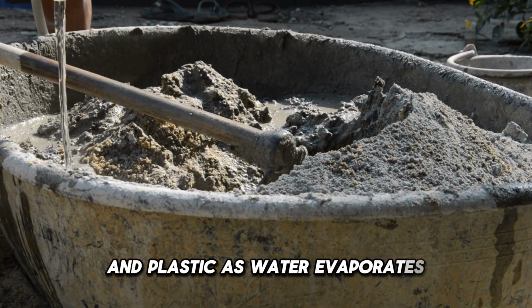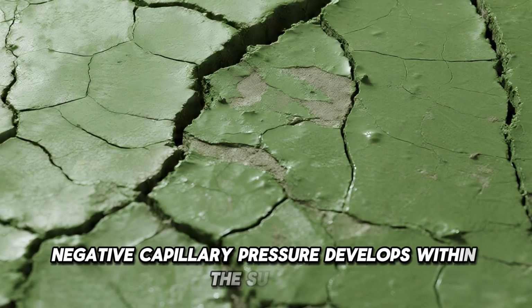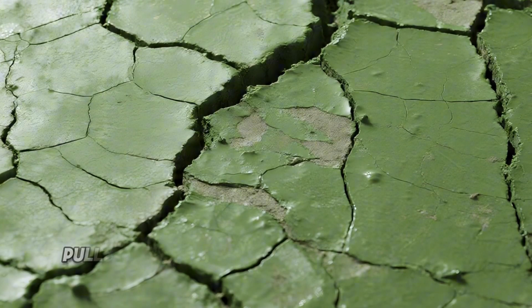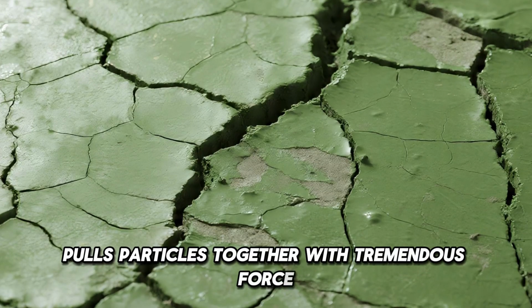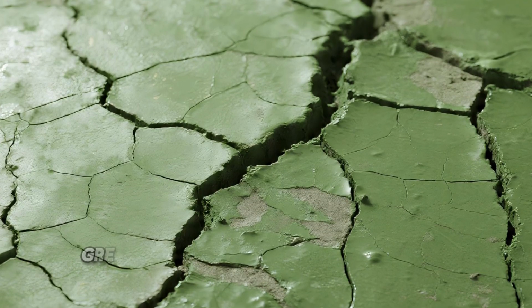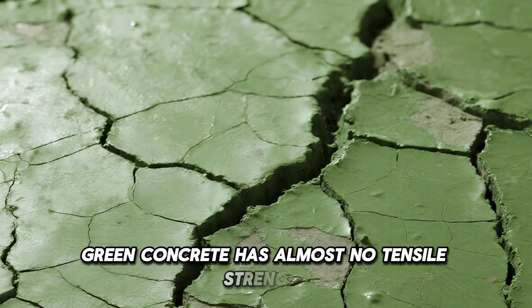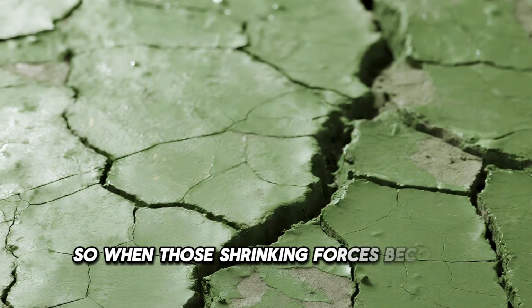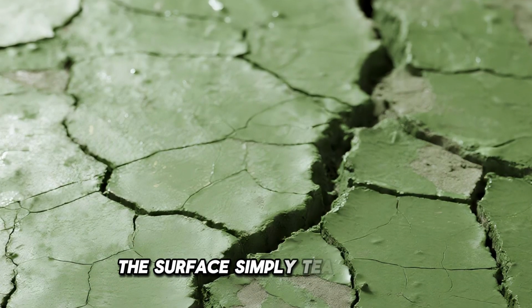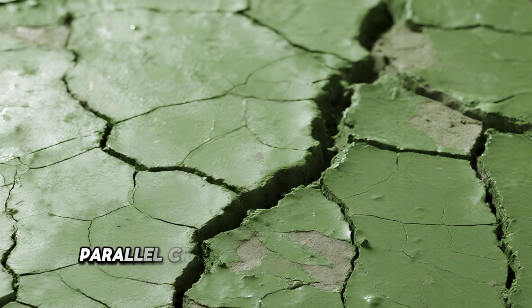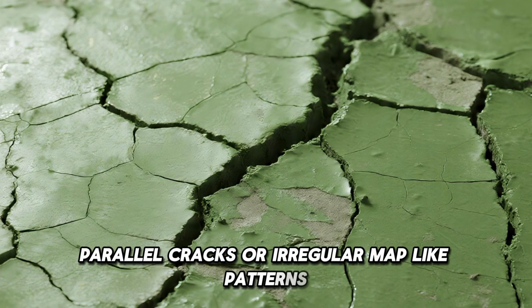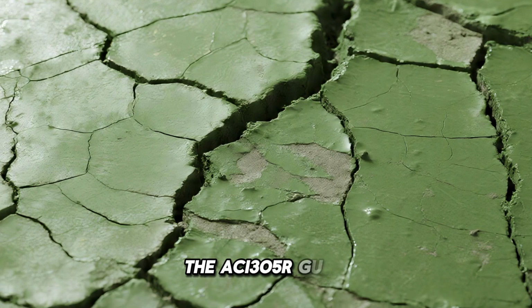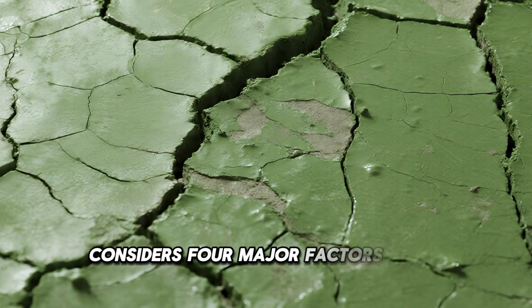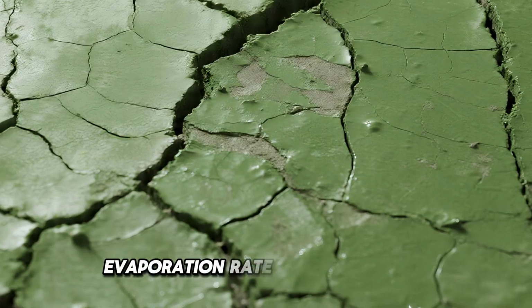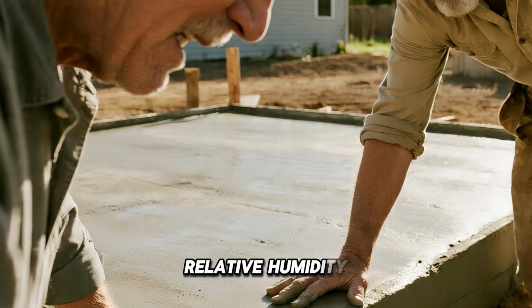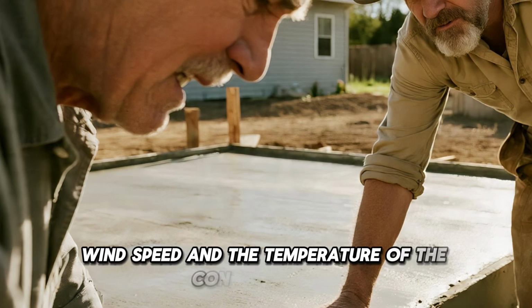As water evaporates, negative capillary pressure develops within the surface paste. That pressure pulls particles together with tremendous force. The problem is that fresh, green concrete has almost no tensile strength. So when those shrinking forces become strong enough, the surface simply tears apart, producing long parallel cracks or irregular map-like patterns. The ACI 305R guide considers 4 major factors when estimating this evaporation rate: air temperature, relative humidity, wind speed, and the temperature of the concrete itself.